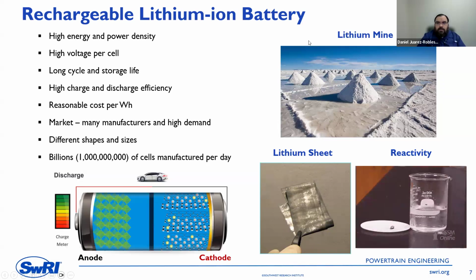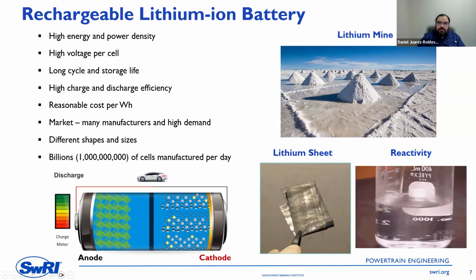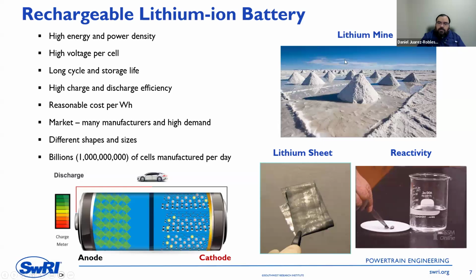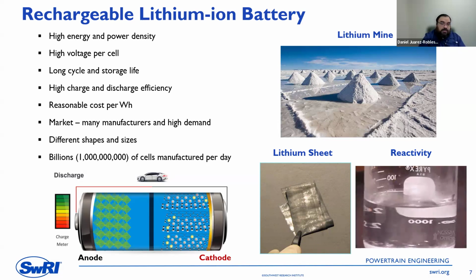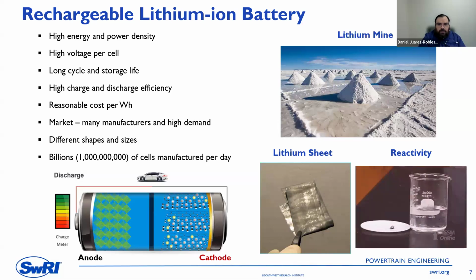Now, just to give you an idea of how lithium looks when you mine it, it looks like a salt. You need to purify it, and once you purify it, you can get a lithium sheet, something like this. That's a malleable metal, similar to lead, that you can bend with your hands, but it's highly reactive. Even if you expose it to a small amount of water or oxygen, it will react and it will turn black. So the black thing that you can see here is the lithium oxide.